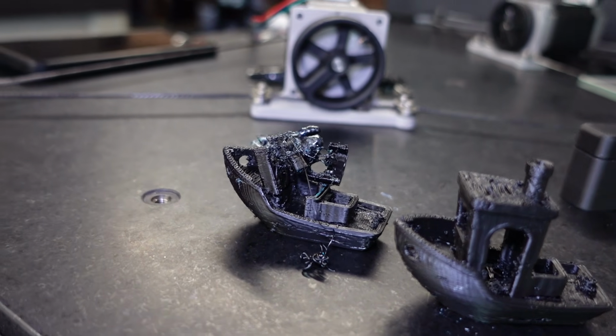Right now my mixing or co-extrusion isn't perfect because the hot end isn't designed to do that. I've just found that out when I was doing multicolor tests a few episodes back. But you can see that despite being 50% of that here being bluish, this is pretty much a black print, so the wrapping around part is basically working for 80 to 90%. And there is a lot of viscosity things going on, so if we choose the lower viscosity for the outside material, the wrapping around will be better.